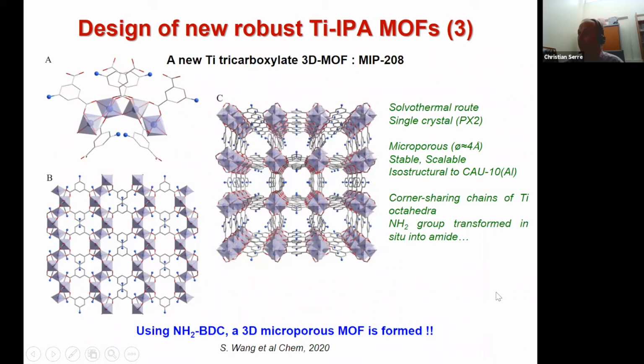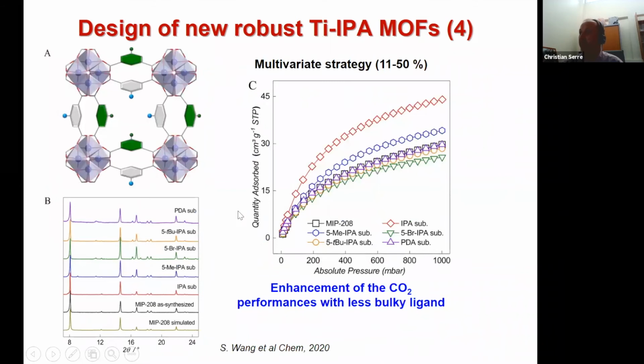So we form a microporous 3D MOF that is also hydrophobic, because you don't have any more OH group in the chain, because you have a μ4-oxo chain in this case. And this material, of course, you can change also by different isophthalic group, up to 50% in some cases, and it changes the CO2 capacity. So this can be interesting for separation, but here this was not our main focus.